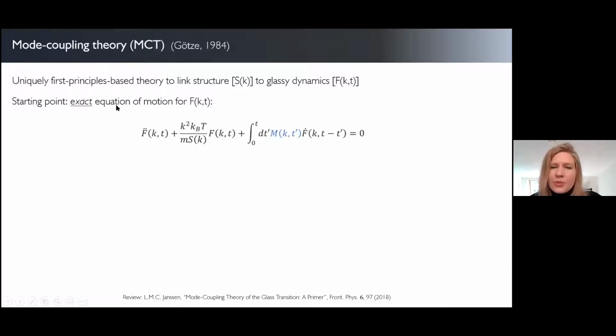So briefly, the starting point of mode-coupling theory is the exact equation of motion for the intermediate scattering function for a glass forming material. So it really starts from the exact microscopic picture of a correlated liquid. And that exact equation turns out to be this integro-differential equation here for F(k,t). So if we could solve this equation for all times t, for all wave vectors k that we're interested in, and all temperatures and densities of a material, then we would be able to predict the full microscopic dynamics of that system, and then in a way we could argue that we have solved that problem, where we can really predict the full dynamics of a glass forming material.